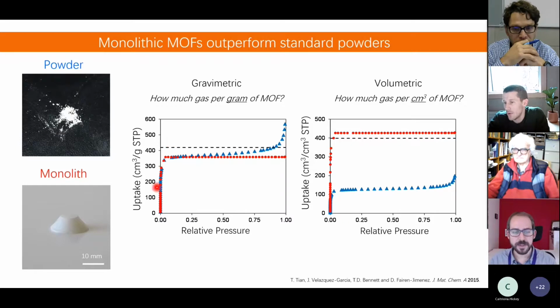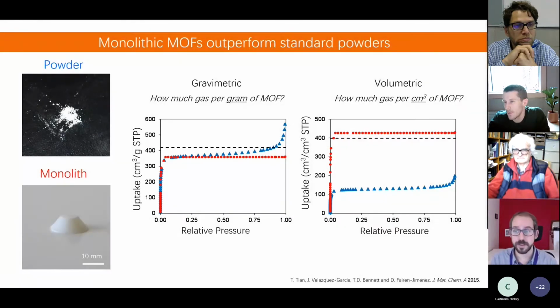This is the BET area. We collect this from this region of the nitrogen isotherm. If we try to calculate the BET area, just looking at these two isotherms, we will see very similar values. There is almost no difference in surface area between the powder and the monolith. The difference is that we transform these isotherms into this volumetric representation. Here it is cubic centimeters of gas per cubic centimeter of metal-organic framework. We are multiplying every single point here by the density of the powder and the density of the monolith.